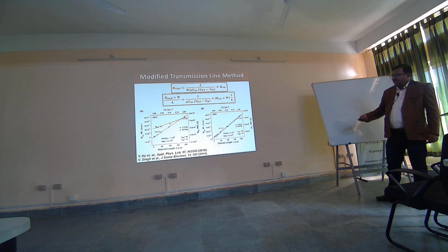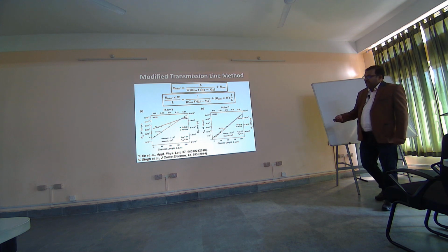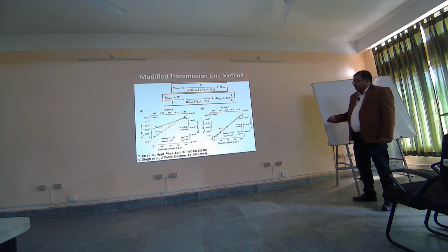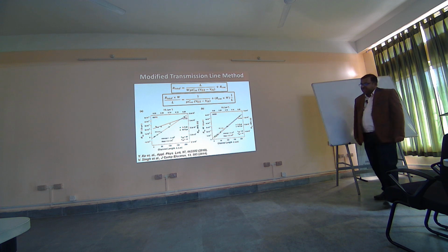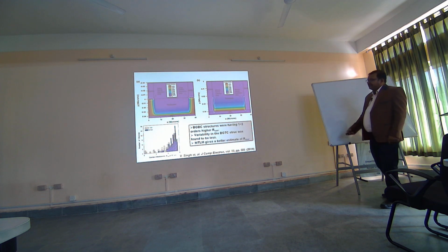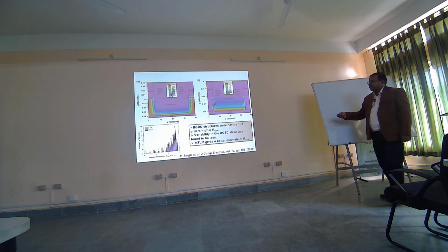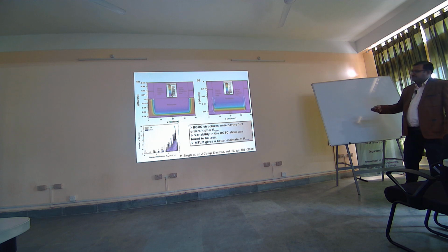We found that the contact resistance was much higher for the BGBC. You see, two orders of magnitude higher slope in the case of BGBC compared to BGTC structures. This is the statistical analysis I was referring to. Then we try to explain these results.